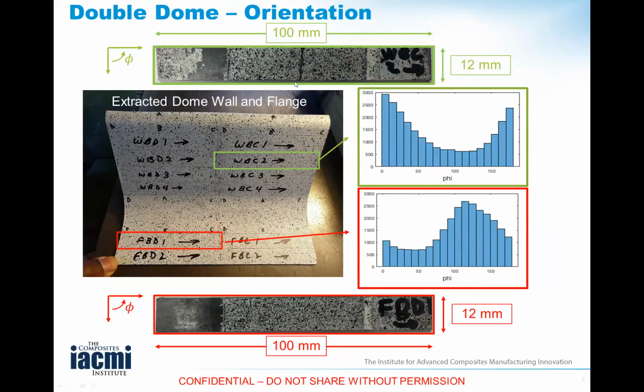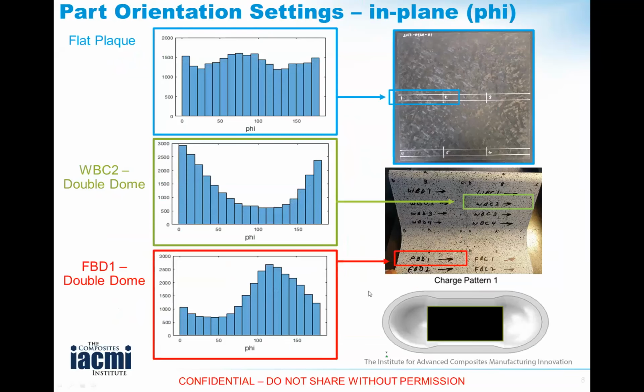And this is an example that Matthew Kant is showing from his work, where if we take the samples from a flange region versus the wall region, the orientation of these platelets is very different, and this essentially controls the mechanical properties. So if you look at the orientations on the flat plaque, you see that the probability of a given orientation is very similar across all the angles. So this is the reason why if I take samples in X or Y or a certain angle, the properties will be very similar for flat plaques.